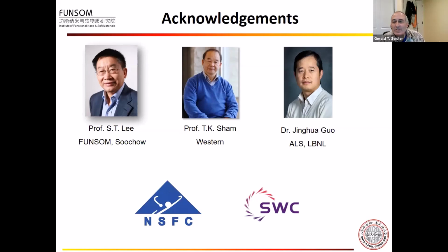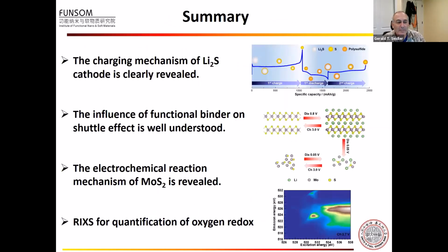Very interesting. First, there was a question that the molybdenum L3 edge is a little bit above the sulfur K edge. Someone was curious if you've ever included the molybdenum L3 edge in your study of the molybdenum sulfide. Actually, I measured the Mo L edge, but I don't know why, the intensity of Mo is always pretty low, and the signal-to-noise ratio is pretty bad. So I didn't show the data. But we can see the edge shift in the results.